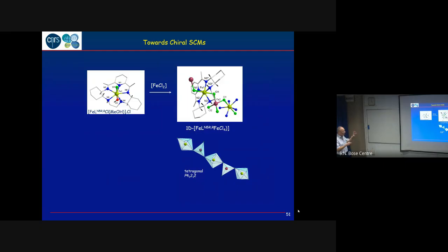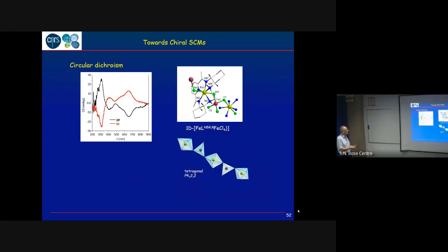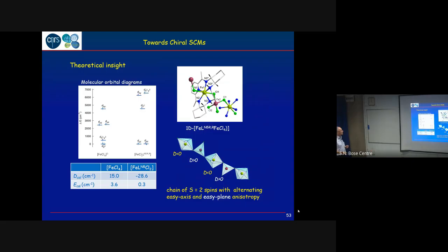I show here only the coordination for the metal centers. And so you have a chain in which you have seven-coordinated and tetrahedral iron, alternating. And for this compound again, because we start with a chiral building block, we can make the R and the S system, and the two are each of the optical isomers you may expect of this chain. This is a chiral chain.